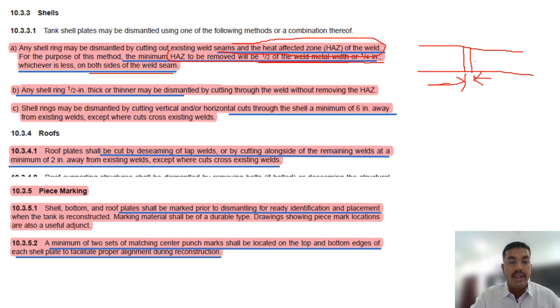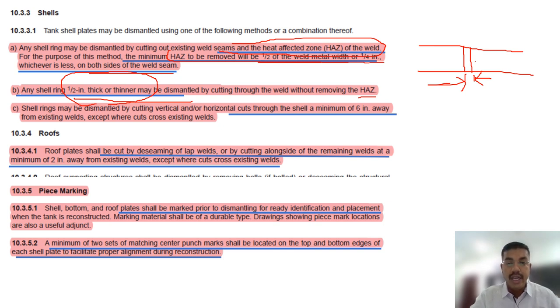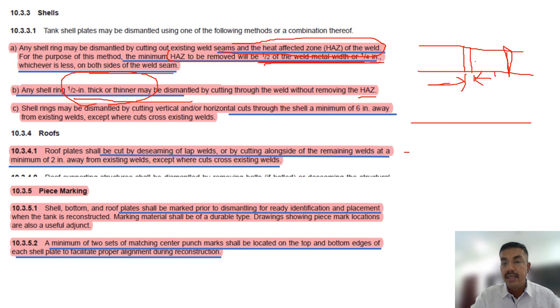If the shell ring is half inch thick or thinner, we can use the heat-affected zone area without applying the half-weld-metal or one-quarter-inch formula. Shell rings may also be dismantled by cutting vertical or horizontal cuts through the shell, a minimum of six inches away from existing welds. For example, if I have to remove a shell plate, I can cut from both sides, six inches away from the weld, then shift the plate and re-weld it at the new location.